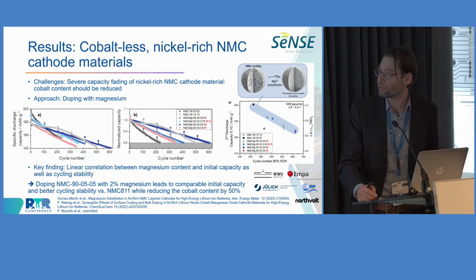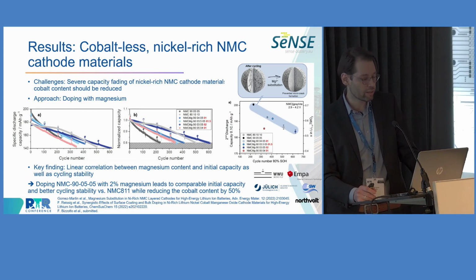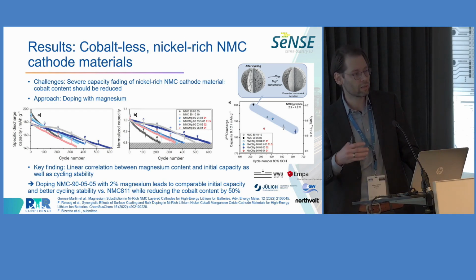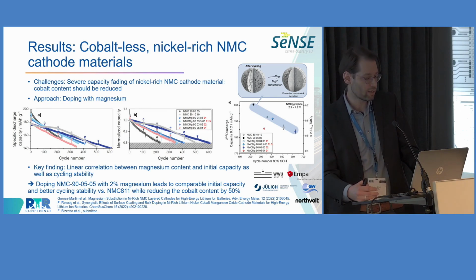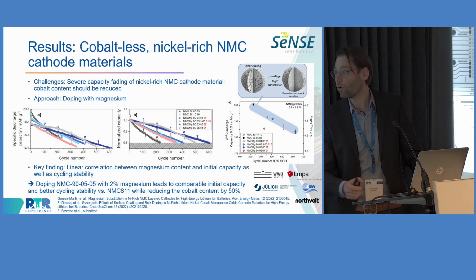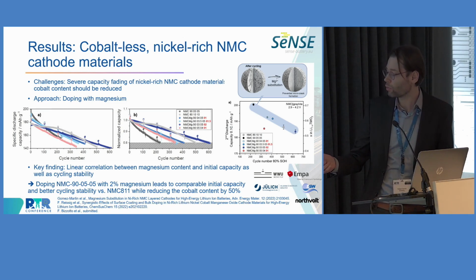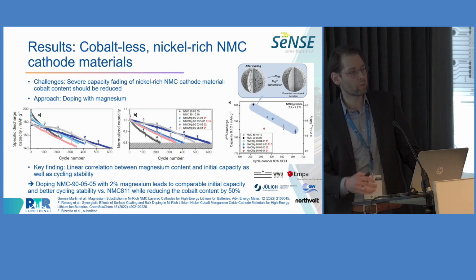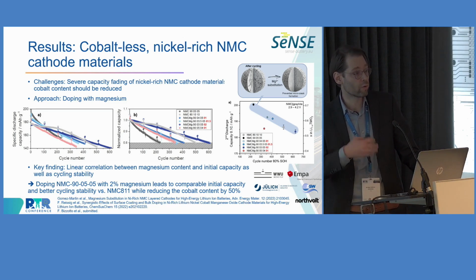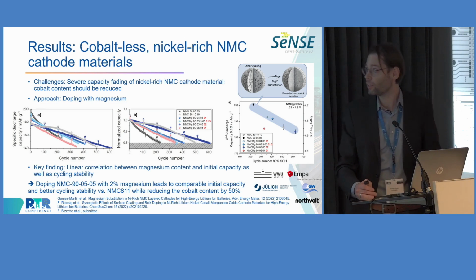the cathode material. So here for nickel-rich NMC, the challenge is really when you increase the nickel content, you gain in capacity, which is nice, so in that way you can increase the energy density. But at the same time, the material becomes less stable. For us, the starting point was NMC 811, so already quite a high nickel content. But then we wanted to go beyond, also in order to decrease the cobalt content, which is one of these critical materials that was mentioned already earlier.